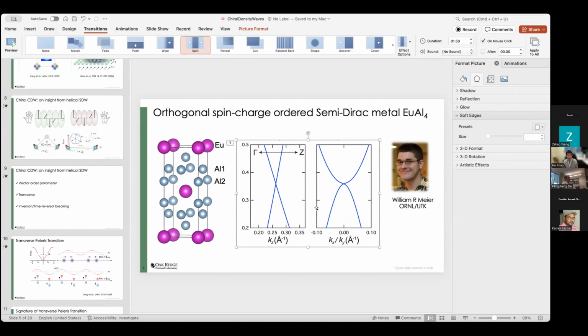The CDW transition temperature shows quite interesting behavior. It first goes down and then goes up. I see, but it's still chiral once you dope it? We haven't checked the chirality yet, but I think for low doping, yes. But for high doping, no, for sure. For low doping, what is your low doping? I think we checked a 10% gallium-doped sample. It's still C4.